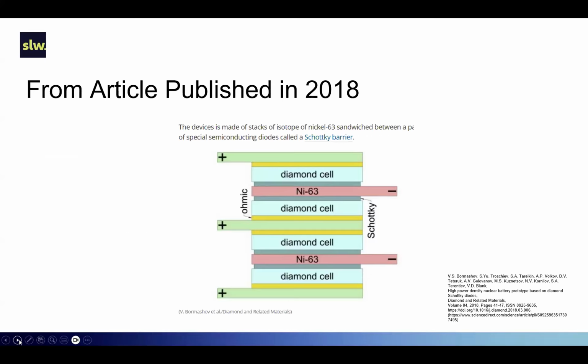So this work was done in Russia, and this is a schematic of their device from an article published in 2018, which made it prior art to the Chinese patent applications. But what you can see is the diamond cell and the nickel-63. What's kind of interesting is they are separated so that the nickel-63 does not actually contact the diamond cell. And that's going to be of interest in a second design that we're going to look at shortly.